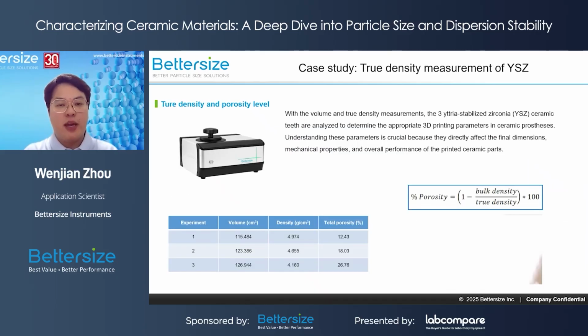Based on the measured volume and the true density, three yttria-stabilized zirconia ceramics were analyzed to evaluate the porosity level of the material to determine the appropriate 3D printing parameters for ceramic prostheses. If the porosity level is high, the green body shrinks greatly after sintering, probably leading to structural issues or non-specific size. Understanding this parameter is crucial because it directly affects the final dimensions, mechanical properties, and overall performance of the printed ceramic parts.